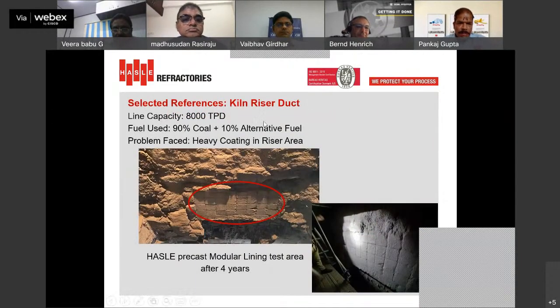This is a plant with 8,000 TPD capacity using 10% alternative fuels. They were facing a heavy coating issue in their riser area. We installed our precast lining here in the riser area, and you can see this picture after 4 years of performance. In the adjacent area where a different castable is installed, you can see the coating pattern. Even after 4 years, there are no traces of coating found on the precast surface.